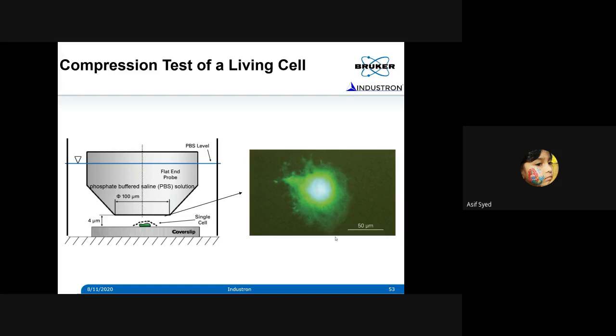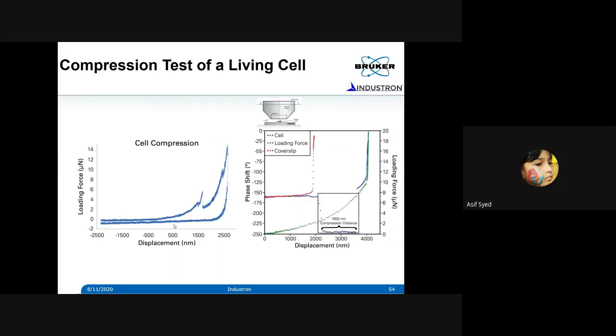Now, as I mentioned, making contact and sensing the contact of the cell is a very challenging thing. When you make contact, you won't feel like you are sensing the contact. So that's why you need to use this phase approach. If you monitor the phase, for example, in this next slide, this is done in a submerged condition using a PBS solution. You see the whole probe is submerged, and you can see that the cell is just beneath the probe, and you are approaching with the probe to make contact.